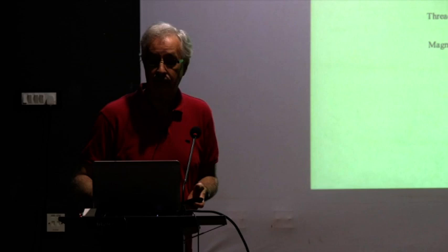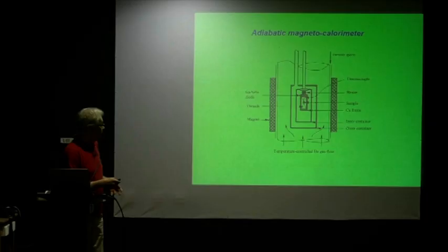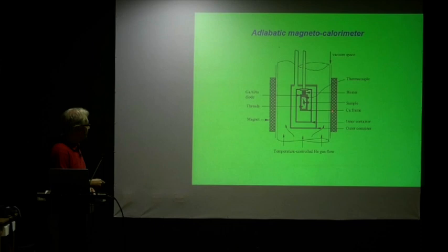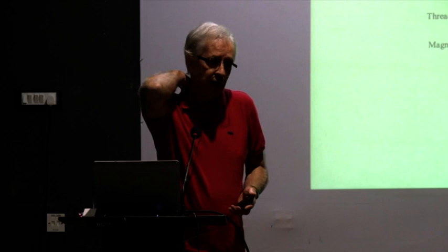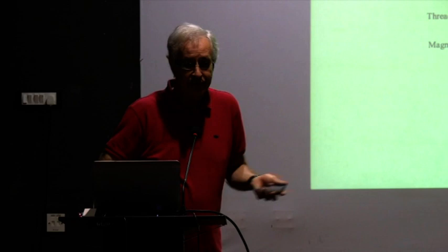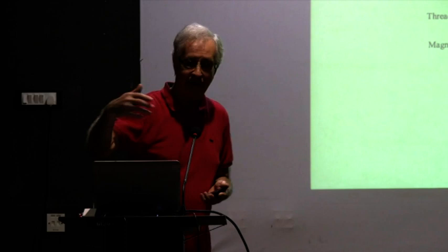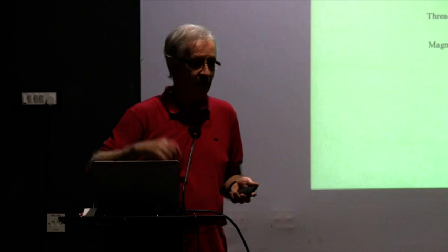So then, outside here, we have our magnet. It's a solenoid. It surrounds the whole thing. And then you apply your magnetic field. It's a superconducting magnet, the one that we had. In some cases, you may have electromagnets. In some cases, you may have pulse magnets. And that changes the speed at which you apply your magnetic field, and that also has effects on the transition properties as well. But anyhow, we're in the simple case where we're just sweeping the field, let's say.